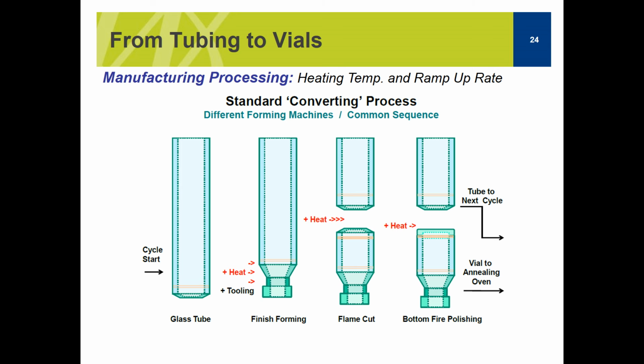So this is a diagram of the manufacturing processes of vials. Basically, you start with a glass tube, you apply heat at a certain temperature and a certain ramp up, or acceleration, of temperature, and you do tooling, and then you have the finished form. So this is the top of the vial, and you convert it, and then you apply heat at the bottom of the vial, and basically you seal the vial, and then you drop this vial, and the cycle continues on to manufacture the next vial. Okay, so the idea here is, can we do anything different in these manufacturing processes that can increase or decrease the probability of delamination? And the answer is yes.